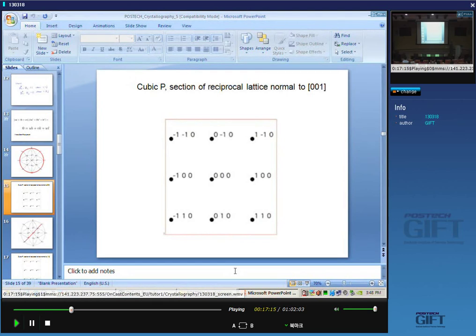Yeah. Now, which do you think has a larger spacing, the 1, 0, 0 planes or the 1, bar 1, 0 plane? Which planes are more widely spaced, 1, 0, 0 or the 1, bar 1, 0? Yeah, because remember it's reciprocal. The magnitude here is 1 upon the spacing, so planes which are spaced far apart will be nearer to the origin of the lattice. Okay, the reciprocal lattice points will be nearer to the origin.